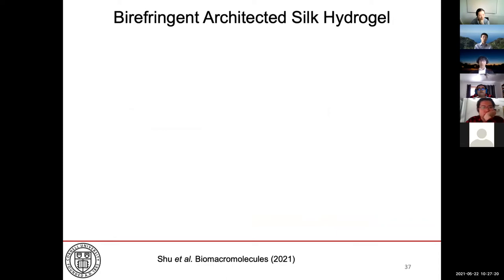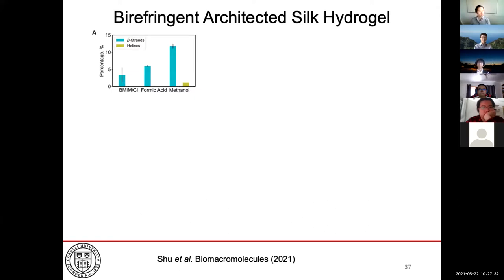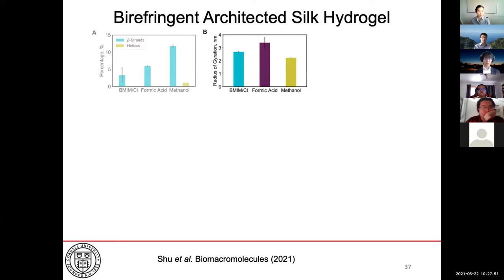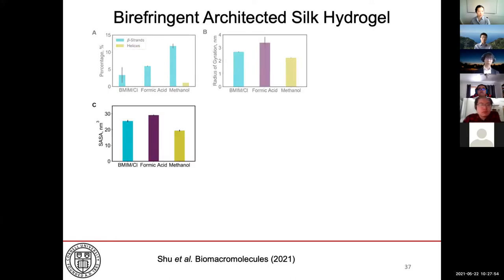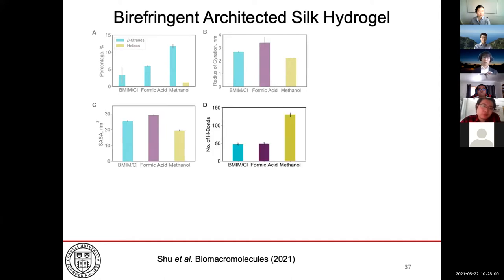And having observed all the different mechanical properties, the electrical properties, now we are also looking into the optical properties. Can we actually tune the optical properties of such silk hydrogels? And it turns out that we can, in fact, again, use different forms of chemical processing of silk to derive different sorts of structures. And using, again, molecular dynamic simulations where we isolated silk in different ionic solvents, in formic acid as well as methanol, we find that we can very finely tune the different secondary structures that are found in the proteins. And therefore, this actually produces different structures where we change the radius of gyration, the solvent accessible surface area, as well as tuning the number of hydrogen bonds.